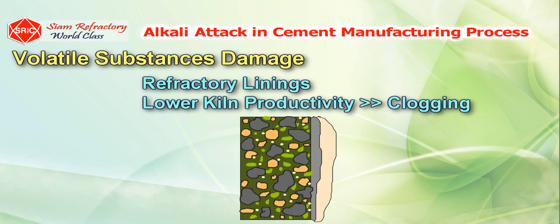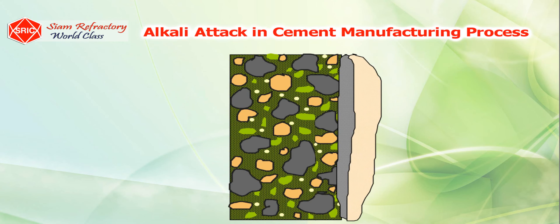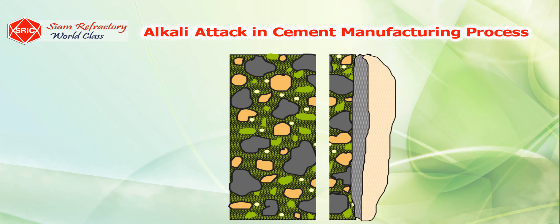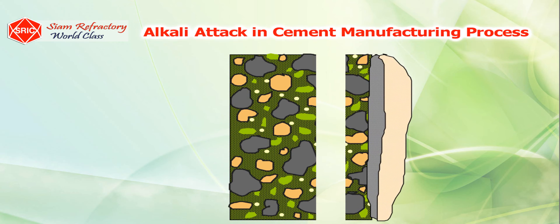Usually, we clean these clogging zones by applying pressured air or high-pressure water. However, these solutions cause the surface of the refractory to fall off, which shortens the service life of the refractories themselves.